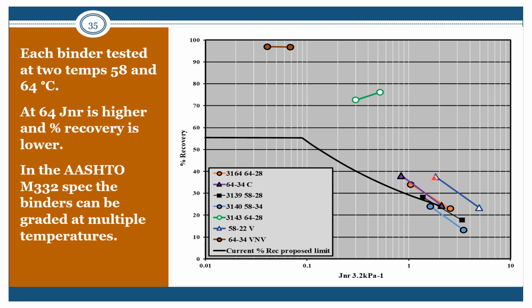But it has a significant amount of recovery, meaning it was probably highly polymer modified, and that's probably why you can see the big shift that's going on here. Now, these other 2 materials here, this 64 minus 28 and the 64 minus 34, you can see that they have extremely significant amounts of recovery, meaning relatively high polymer modifications in these materials, probably a lot of cross-linking. This particular material here,